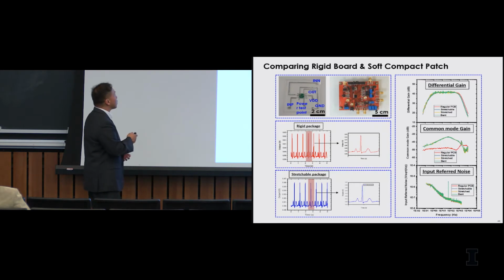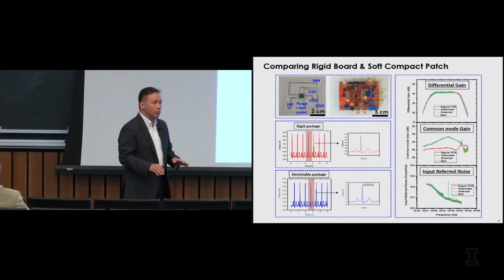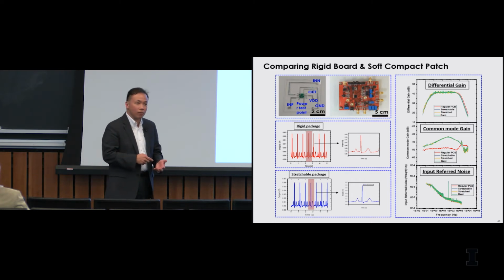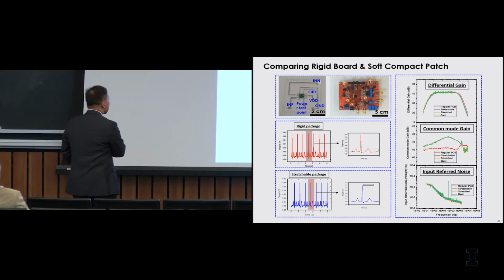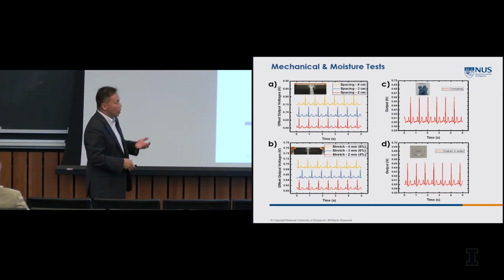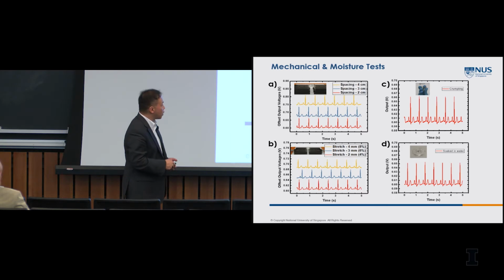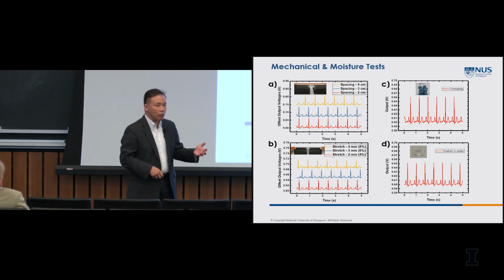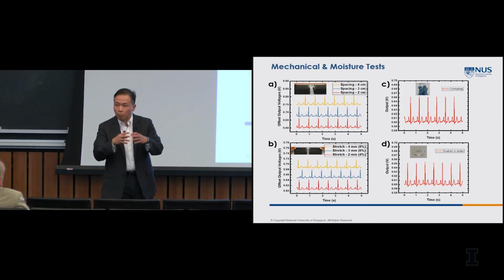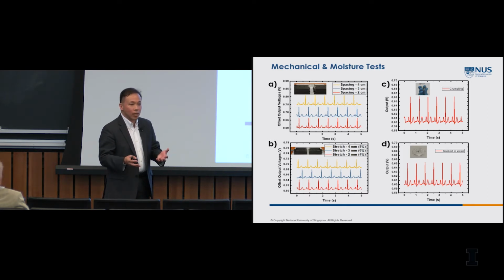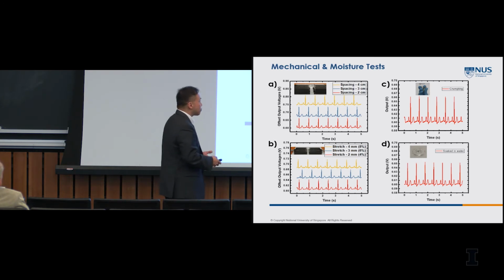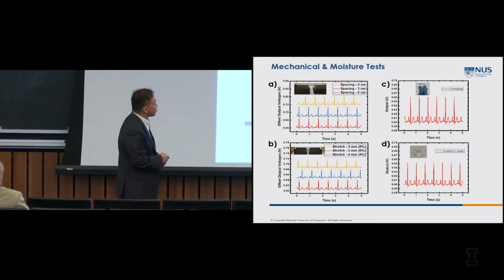Now, it's kind of neat because we tested this against a mock-up in a rigid form. And the key message of this slide is that the rigid package and the stretchable package perform identically. No issue. Of course, the flexible package has other interesting properties that the rigid can't achieve. You can bend it, stretch it, and it continues to function. So it's very robust, okay? And we even soaked it in water. We haven't boiled it yet, but we are going to do that. So the board itself now becomes a packaging solution, and it basically inherited functionality. And that functionality is encapsulation on top, right? So that is the interesting part of this integration.